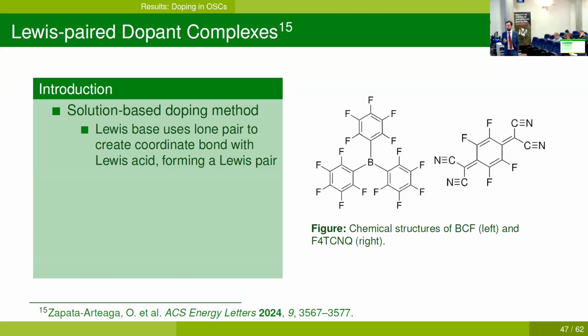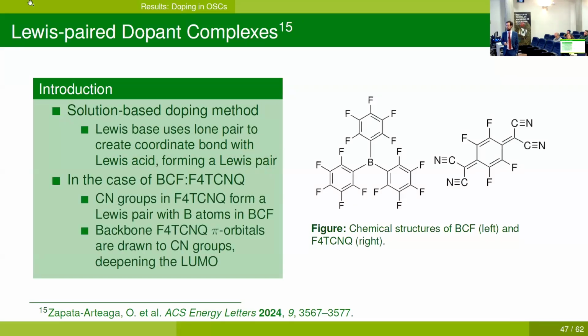Okay, Lewis pair doping is a solution-based doping method where we use a Lewis base and a Lewis acid in conjunction. And what happens is that the base uses its lone pair to create a coordinate bond with the acid, forming a Lewis pair. In the case of these two molecules, which we call BCF and F4TCNQ, the four cyano groups in the F4TCNQ are able to form a Lewis pair with the boron atoms in BCF, this one.